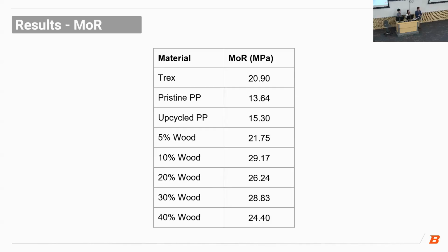And so you have polypropylene, Trex is HDPE. That is correct. Or PVC. It's HDPE. And virgin HDPE or PVC compared to virgin polypropylene. Is that what you expect? Not quite. So we did the pristine or virgin polypropylene compared to upcycled polypropylene, because ultimately the goal here was to evaluate if Boise Cascade could make a viable composite material using the waste streams that they had. And they have polypropylene, they don't really have HDPE. And so even though a lot of the industry players currently use HDPE, really we're trying to investigate if we could use a different polymer and achieve similar results. So we were mainly focused on the behavior of polypropylene to evaluate it as a candidate rather than to evaluate if it was the best option for whatever use case scenario it may be used in.